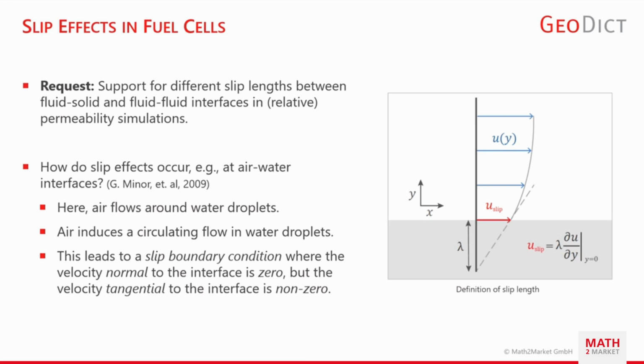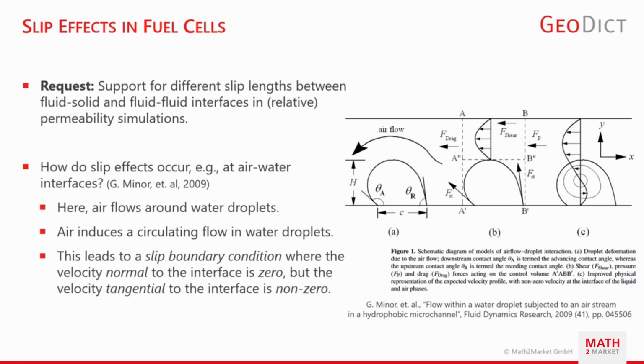And usually you use this kind of boundary condition if you have, for example, thin gas, and if you have small pore sizes. But it seems to be also important in fuel cells. And how can that be? So on the right-hand side, you see an image from a paper. Here you see a flow channel with a water droplet, and you have airflow around this droplet, and you see that the droplet is not moving. It's stationary. So the interface is fixed, but you see that the airflow deforms the droplet a little bit. So you have different contact angles before and after the droplet.